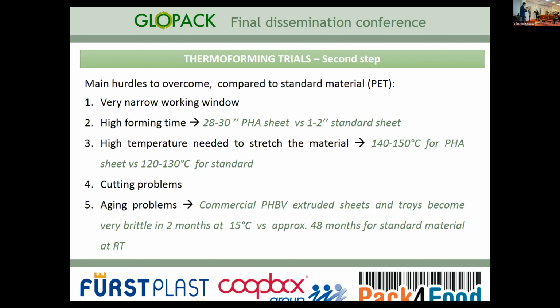If you work with low time and low temperature, the material is not stretchable, so you are not able to thermoform. If you go too high with the temperature, the material becomes liquid, so it's also not possible to thermoform it because it's no longer solid. And for this material, this processing window is very narrow. It's not easy to find the good conditions.